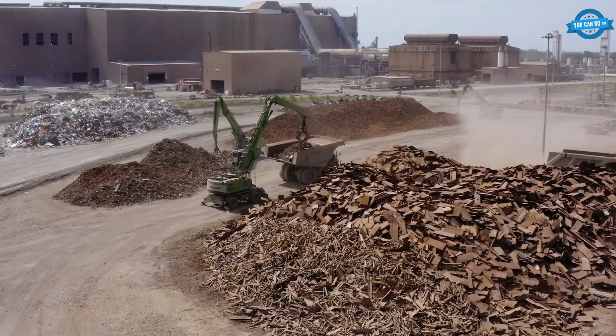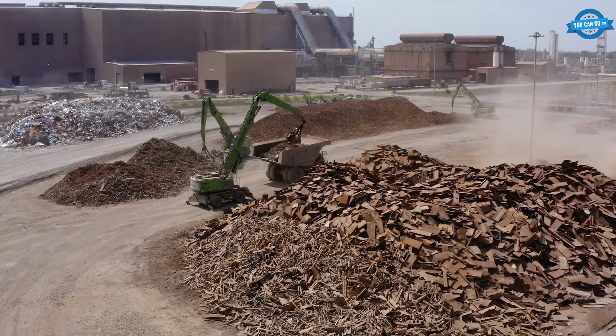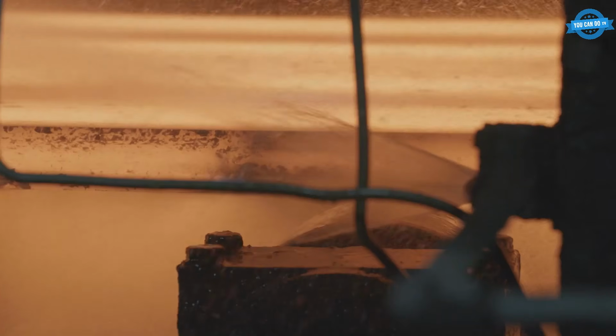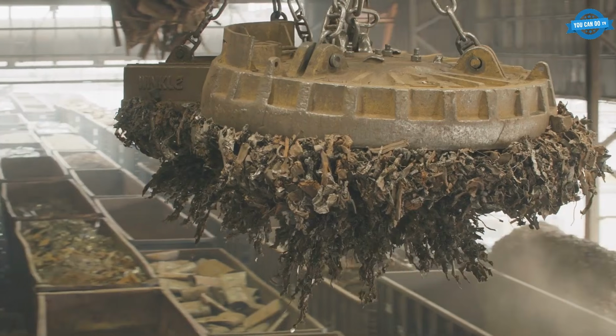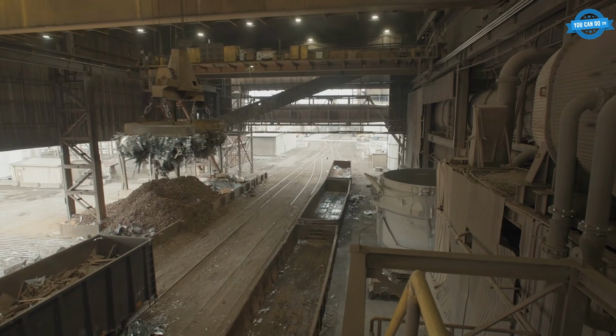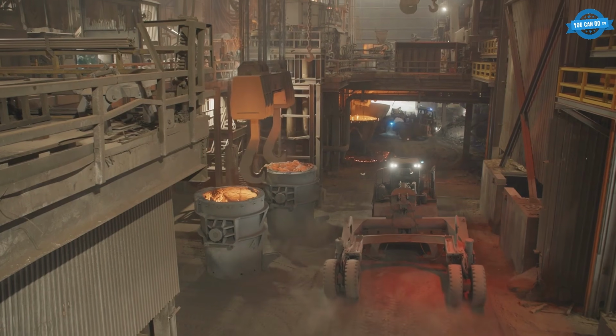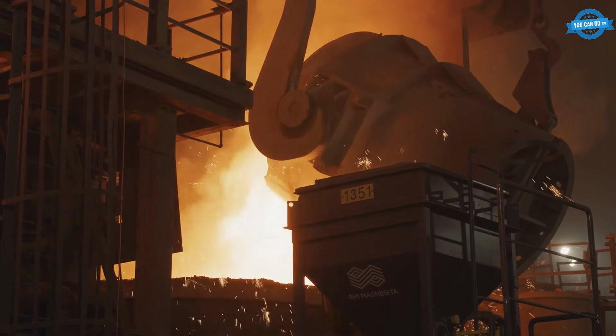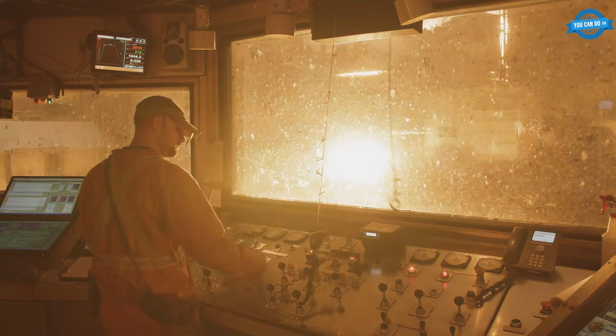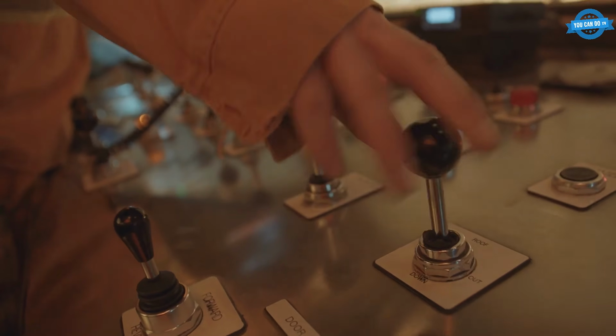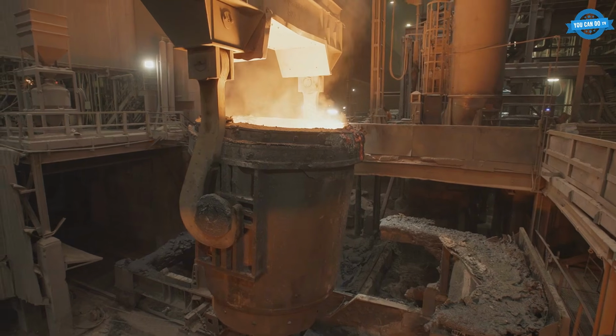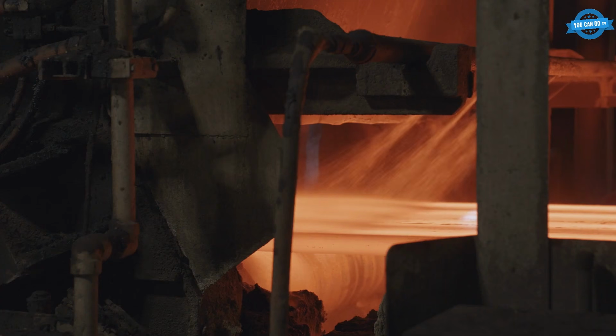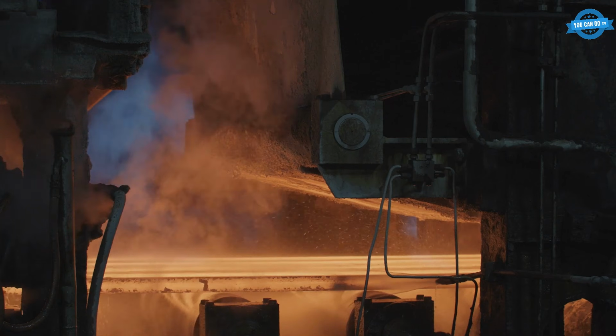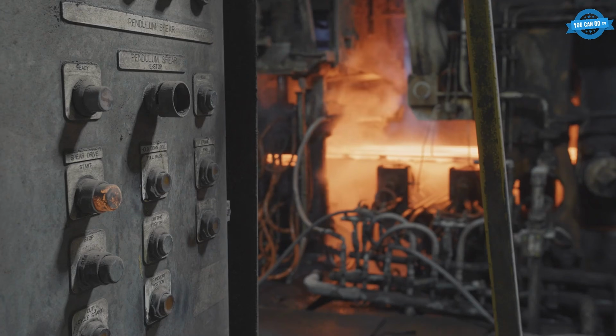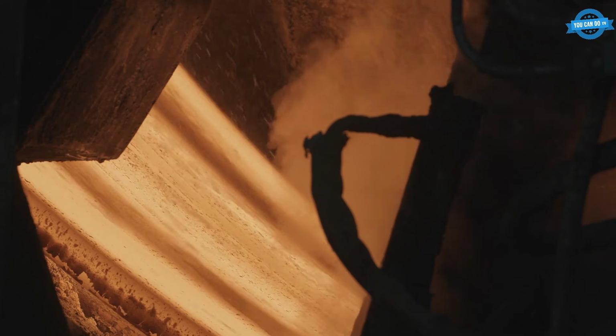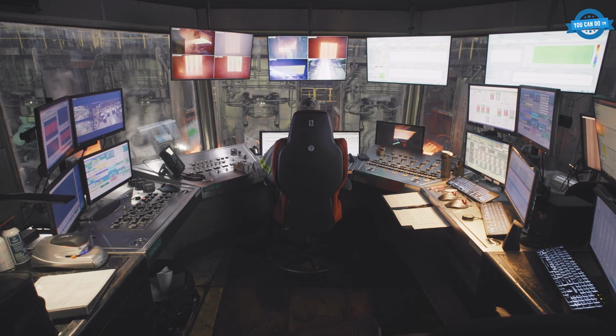Mills blend scrap like a recipe. A single flat roll steel plant can produce over 3.2 million tons of hot metal per year using recycled ferrous scrap as its main input. The charge bucket for each heat mixes heavy melting steel, shredded scrap, structural cut, and specialty grades in exact proportions to hit target chemistry. Operators check the mix, adjust ratios, and log every source lot for traceability. Modern steelmaking is basically industrial cooking at a scale where every burner runs at 3,000 degrees. Get the recipe right and the melt behaves. Get it wrong and the whole heat has to be scrapped.